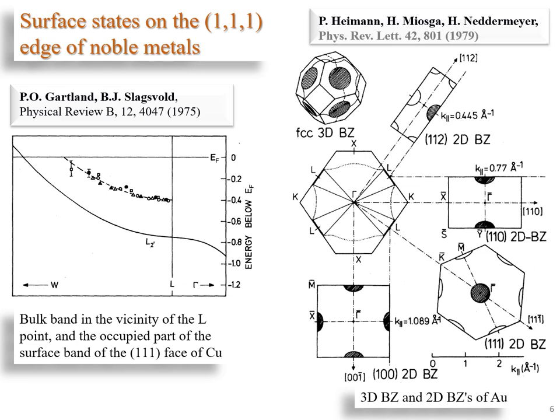In this slide, we see dispersion of surface states, experimentally observed by angular resolved photoemission in the (1,1,1) surface of copper and schematic projections of 3D Brillouin zone of gold on different crystal phases and resulting 2D Brillouin zones. The projections of the open Fermi surface necks are shown as shaded regions, where surface states exist. For (1,1,1) phase, they emerge in the center of 2D Brillouin zone, while for some others they also exist, but near the edges of the respective 2D Brillouin zones.